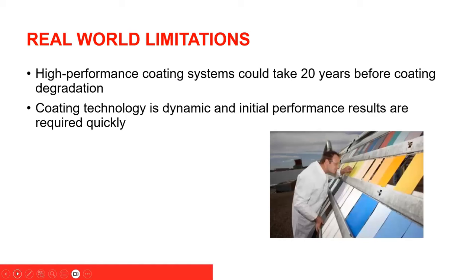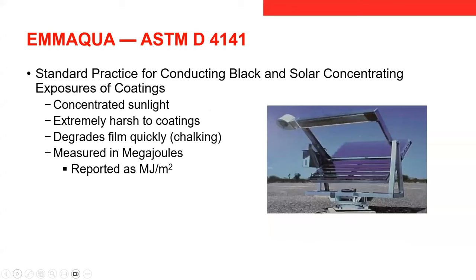And as I mentioned, high performance coating systems can take 20 years before coating degradation. So as a manufacturer, we test using accelerated testing, because you get results a lot quicker. EMMAQUA is a standard practice for conducting black box solar concentrating exposures of coatings. This provides concentrated sunlight that is extremely harsh to coatings, and it will show degradation really quickly in the form of chalking, and it's measured in megajoules per meter squared.